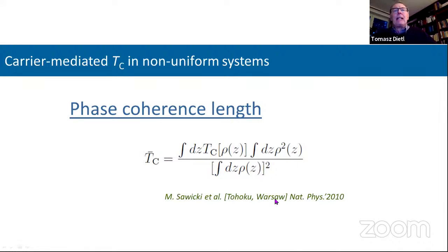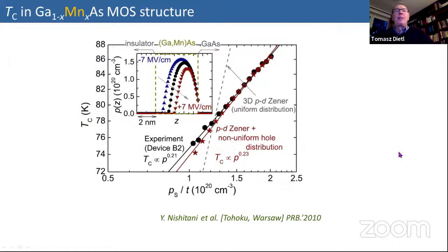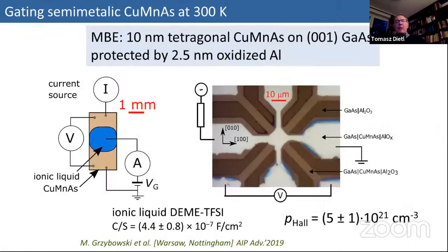So here it's just TC, measured as a function of hole concentration, total hole concentration, which is changed by gate voltage. And if you forget about what I said about this non-locality of quantum mechanics, you get something like that. But if you properly take into account this non-uniform distribution, you can obtain quite good agreement with experimental results. So now, as the next effect, just to change gear.